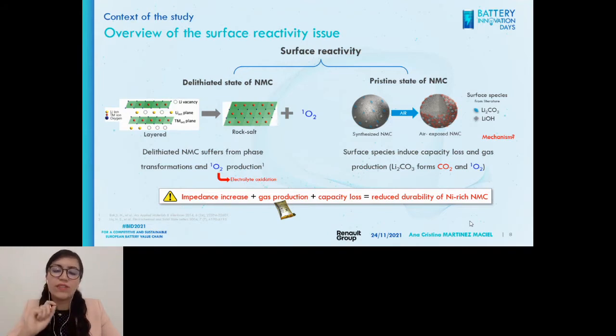And the other surface reactivity issue occurs at the pristine state of NMC. We know that NMCs are sensitive to air, and this is especially important for high nickel content. As a consequence of this air exposure, they will produce carbonates, hydroxides, and oxides. The thing is that the mechanism was not clear in the literature; it was just assumed that they are produced. But it is very bad because as a consequence of this air exposure, there is capacity loss and gas production.